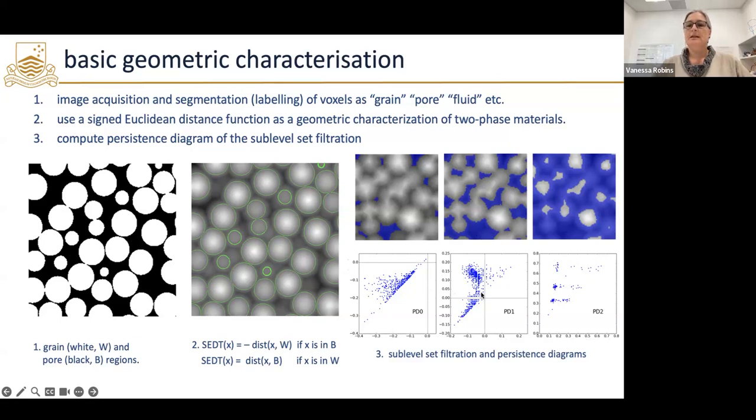Most of our degree 1 persistent homology is in the negative birth, positive death. So that means these sorts of cycles are the ones that go around the grain contacts. Okay, you can't see these because I don't have the 3D picture, but you can think of these points here as representing cycles around the point where two beads are in contact.